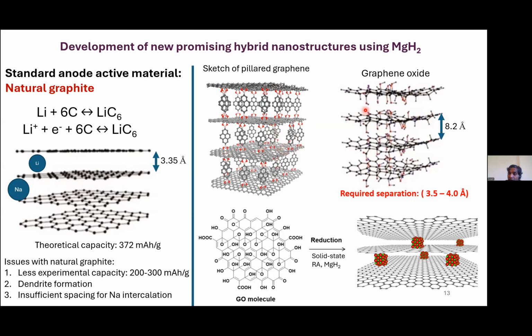And then our attention went to graphene oxide, because graphene oxide is one of the most promising. It's not a natural material, but whatever artificial material is synthesized in the laboratory, graphene oxide is a good intercalation, good pillared structured material. But its interplanar spacing is 8.2 Angstrom, which is very high. And also, the planes are too crowded with several functional attachments, and that will not give sufficient space for the intercalation of either sodium or lithium. So what you have to do is eliminate these functional attachments, and therefore it can come closer. It should not end up with graphene, but at least reduced graphene oxide. So some functional attachments can be there, and you need to get an expanded space.